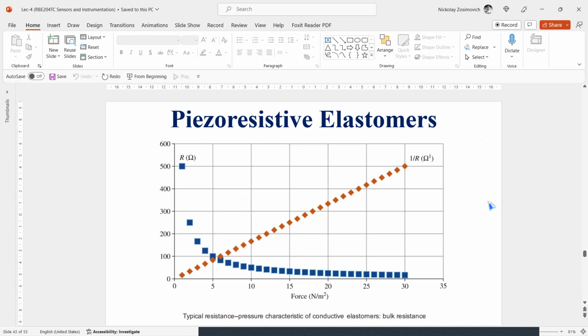Piezoresistive elastomers are a sort of elastomers that are made conductive by impregnation with conductive particles like carbon and silver. The resistivity depends on the concentration of conductive particles, their mutual distance, and the contact area between touching particles. When the material is pressed, more particles make contact, tending to decrease the resistivity of the material. And the resistance between two adjacent or opposite points of the elastomer layer changes in a nonlinear way with the applied pressure.